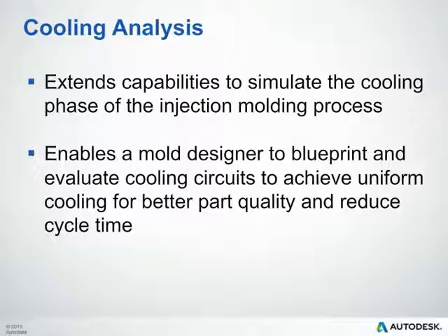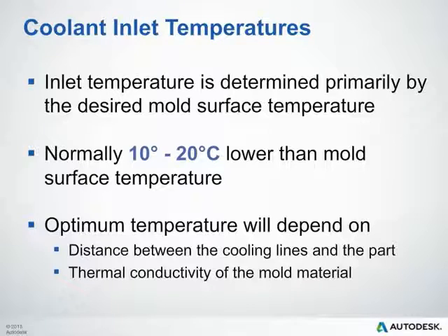The cooling analysis extends our capabilities to simulate the cooling phase of the injection molding process. This enables the mold designer to blueprint and evaluate cooling circuits, achieving uniform cooling for better part quality and reduced cycle time. Your coolant inlet temperature is determined mainly by the desired mold surface temperature — typically set 10 to 20 degrees Celsius lower than the target mold surface temperature. The optimum temperature also depends on the distance between your cooling lines and the part, as well as the thermal conductivity of the mold material.